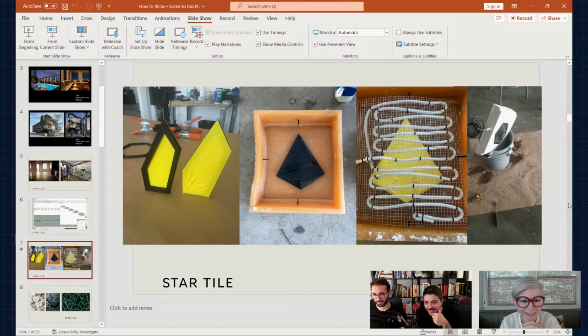So this is the mold, right? Yeah. These are the positives on the left. That's another Pentagon series. Again, we had no idea what we were doing. Pouring this, there's an air hose in it. We use a type of plaster that has fissures in it so the air can shoot through. We pour the plaster with the air hose, and then we sweat the mold, and that 3D printed piece pops out, and then we put the clay in that mold and connect it to a compressor. Doing that, we can make a couple hundred tiles a day with each mold.